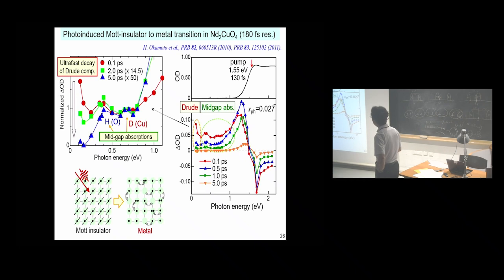Here we expanded the infrared spectra in a normalized scale. Just after the photoirradiation, absorption monotonically increases with decrease of energy, showing a metallic behavior. This suggests that the insulator-metal transition occurs. However, this Drude-like response decays very fast, and after a few picoseconds, the spectrum is dominated by the mid-gap absorptions, which can be assigned to the residual doublons and holons, localized by the charge spin coupling. In the near infrared region, a peak structure is observed, which is attributable to the heating of the system, since this spectrum is very similar to the absorption change due to the temperature increase shown by the gray line.